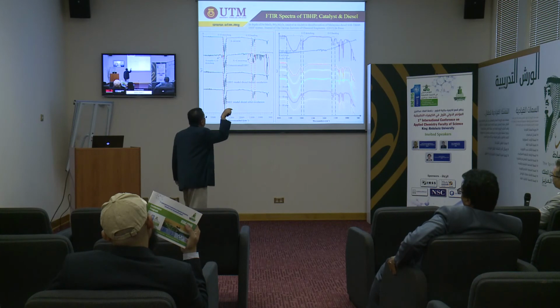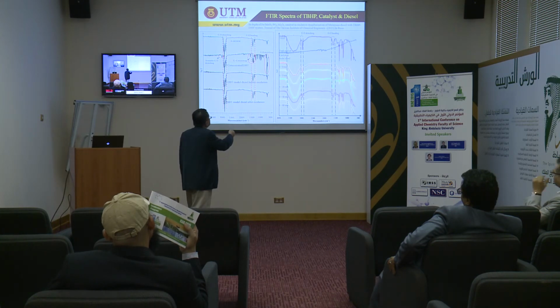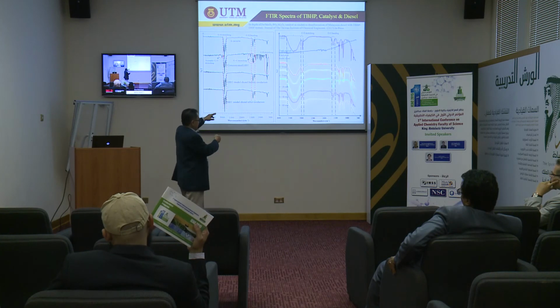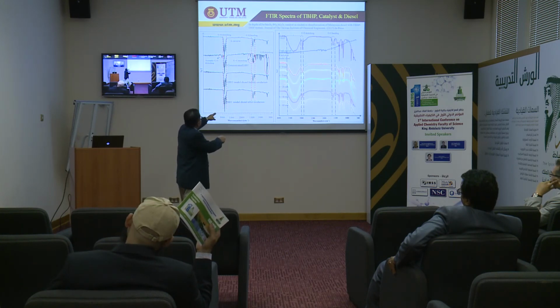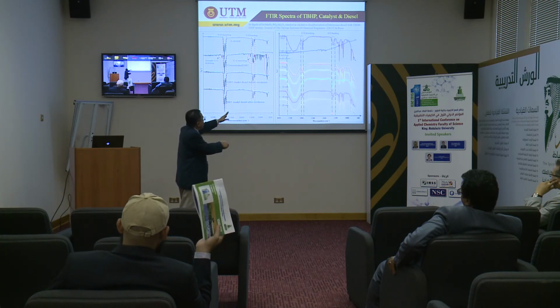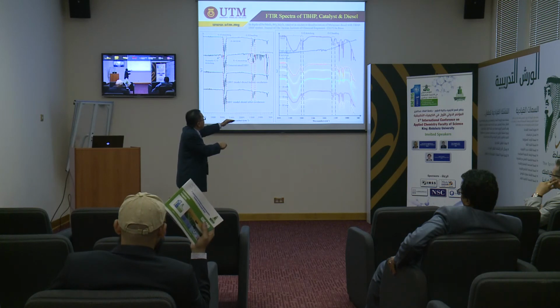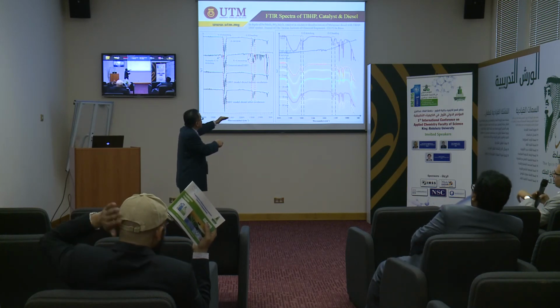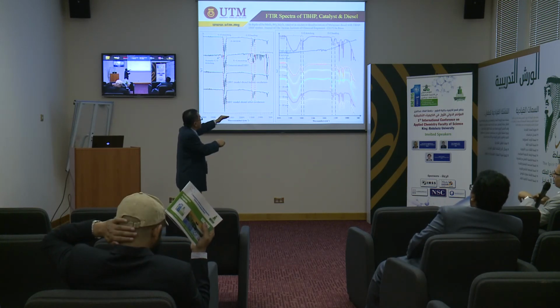If we add in what they call the catalyst, what happened? Only the oxidant is adsorbed on the surface. Okay, you see, adsorbed on the surface. At 30 minutes, it is very high. After that, it decreases, meaning that this is the maximum adsorption of the oxidant on the surface.